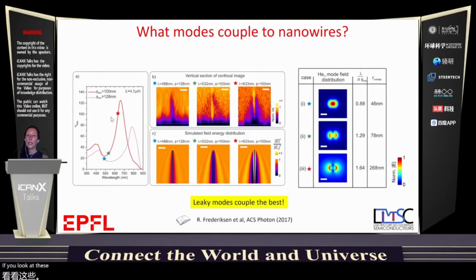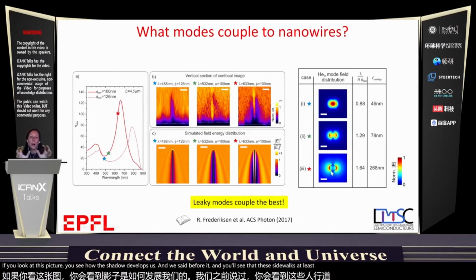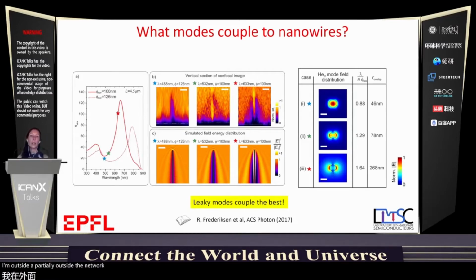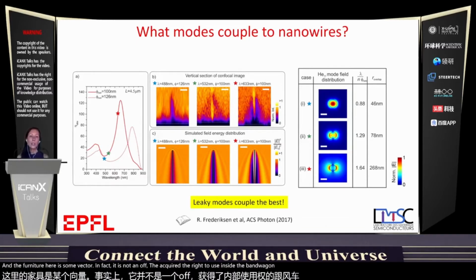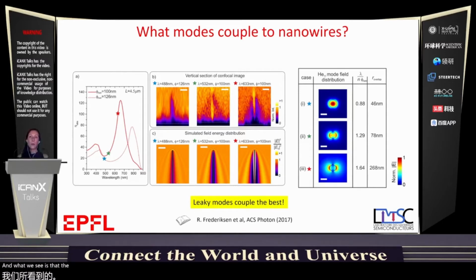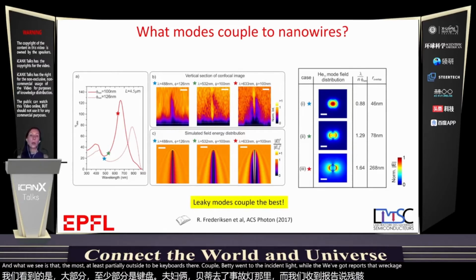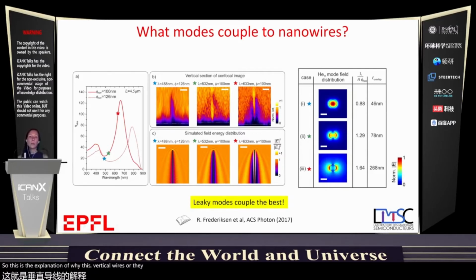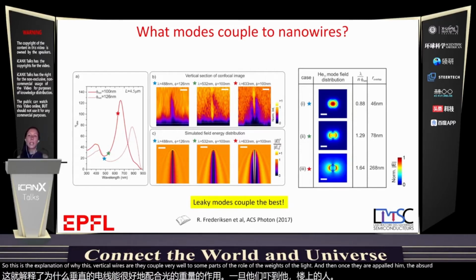On the contrary, if you look at this high absorption peak here, you see how the shadow develops, as we said before, and you see that these are modes that live partially outside the nanowire. These are called leaky modes. And the explanation here is, in fact, it's not enough where the light is inside the nanowire, it's about the coupling. What we see is that the modes that live partially outside, the leaky modes, couple very well to the incident light, while the waveguiding modes are very difficult to couple, and that's why they absorb so little. So this is the explanation of why these vertical wires couple very well to some parts of the light, and then once they are coupled in, they absorb the light very strongly, and so this makes them very good structures for light absorption.